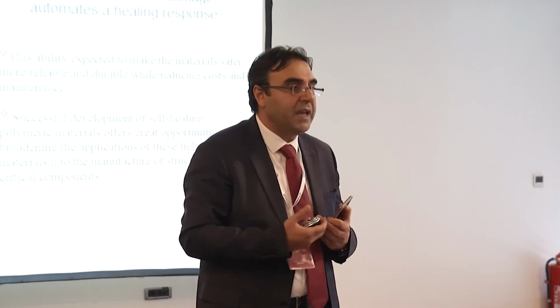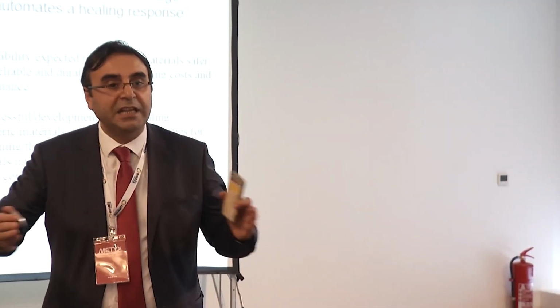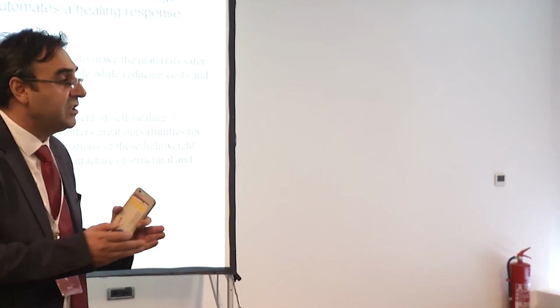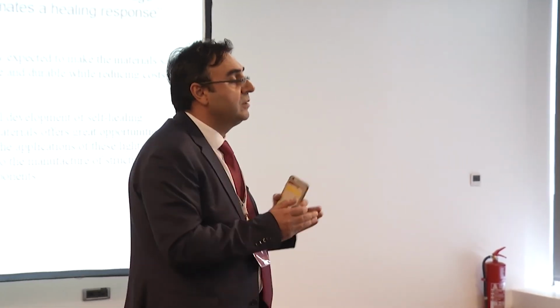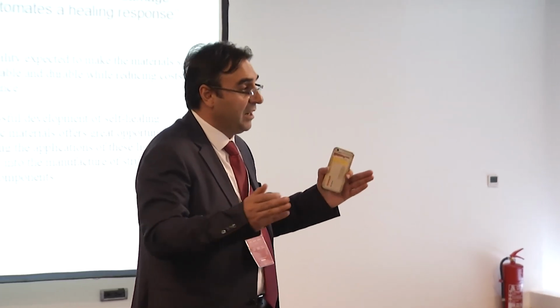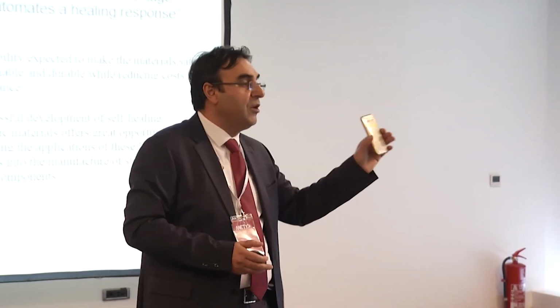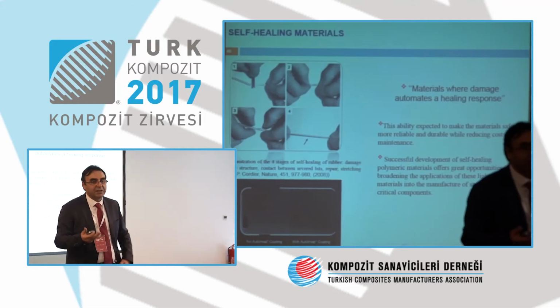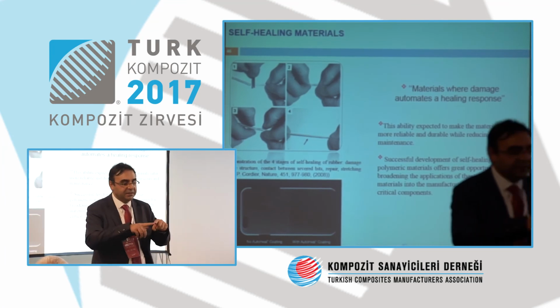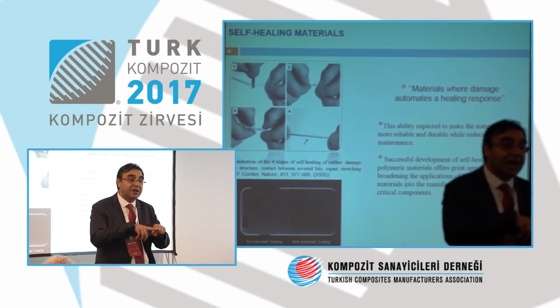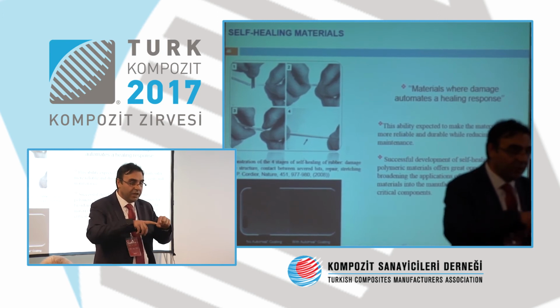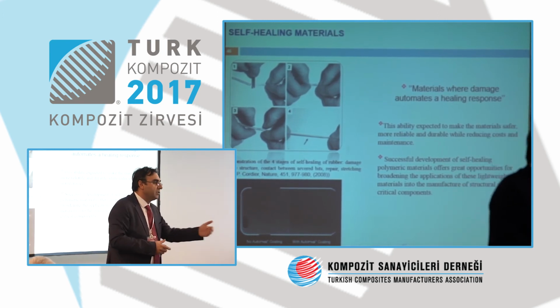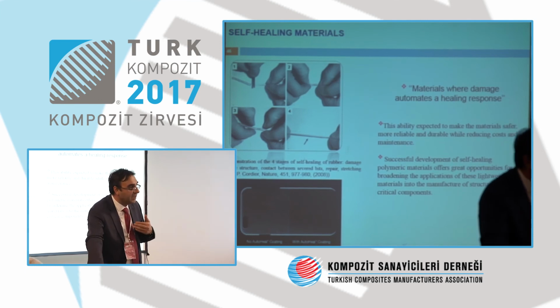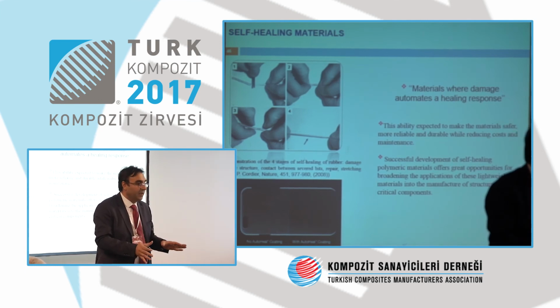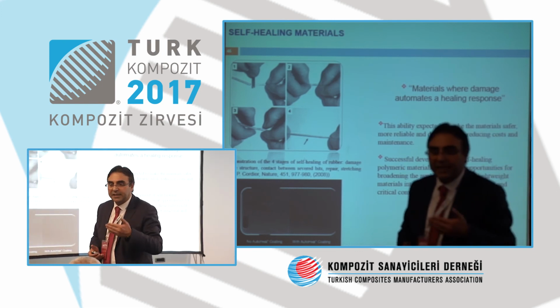For that, what we have done is create vascular networks in our composite structure, which is formed by nanofibers. When I say nano, really they are nanofibers. Of those two fibers, one contains resin, another one contains the hardener. So when we have a crack in the system, the crack comes because the stress at its tip is much larger than the local stress. So it breaks the fiber. Both the resin and hardener leak out and repair the crack region.